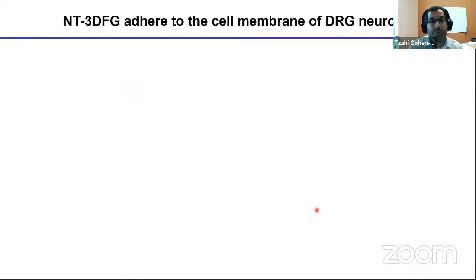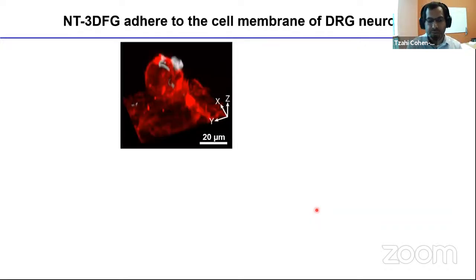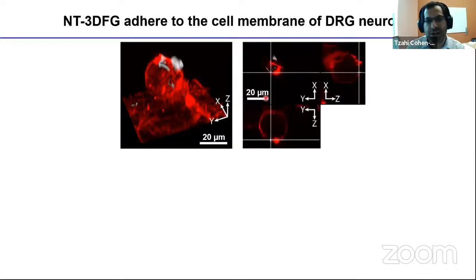Here is how we are interfacing these wires. You take this fuzzy wire, you alter the surface of the wire with a self-assembled peptide to render it positively charged, and then it will stick to the cell membrane. I said that the wires are black. The reason you see them white over here is because we reversed the contrast, so you'll be able to see it in this laser scanning confocal image. You can see that the wires are just attached to the cell membrane outside.